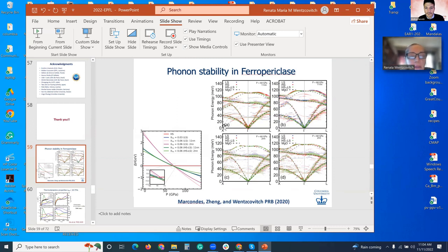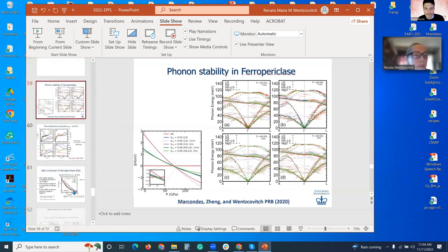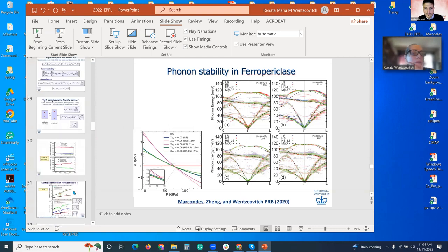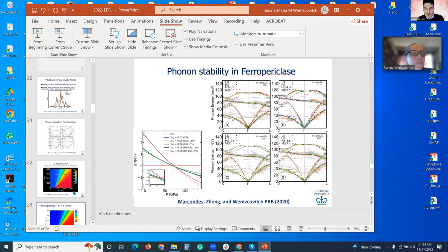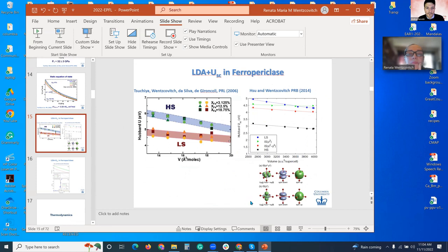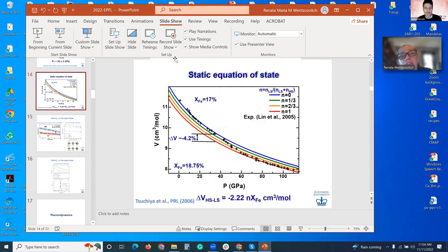As I said, let me show you. Go back here, perhaps. I think even with the non-self-consistent U, here, for example, look, U changes upon self-consistency. The high spin U decreases by 3 electron volts. But the compression curve, this is experiment, and this is calculation. Blue is high spin, red is low spin.